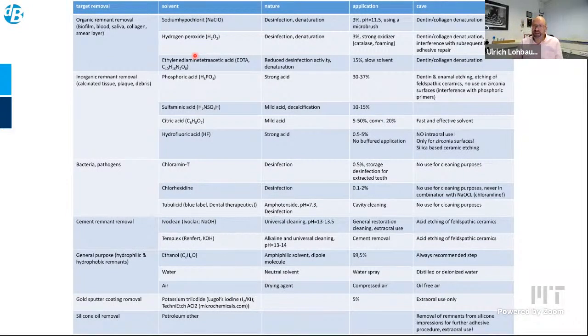At some point, like in dentistry, you have a contamination or a modification of dentin or the collagen layer in dentin, so you need to be careful using those materials on a surface that involves dentin or organic parts of the dentin. Then inorganic remnant removal with acidic or alkaline removals. This is very much recommended. Phosphoric acid, for example, is very common in dentistry, so we use it for cleaning purposes, but it's also etching the dentin and enamel structure. So we need to be careful. On a ceramic surface, it's much more recommended. Then we have bacteria, viral cleaning. There is disinfection necessary, probably before we receive any part from the clinical application.